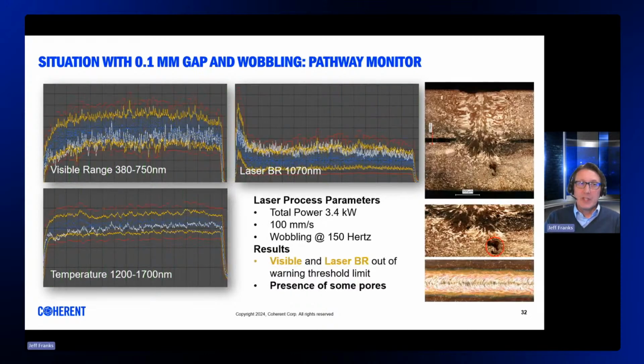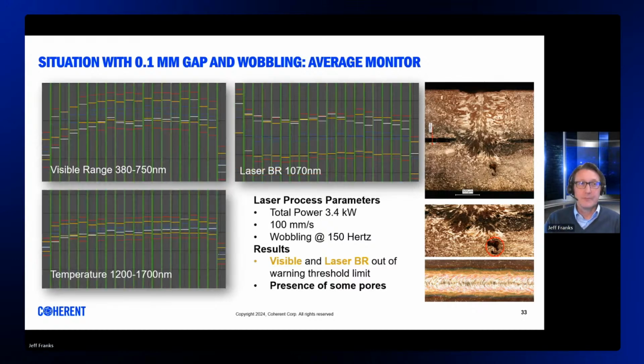Now we can see the effect when we reintroduce the gap condition to the wobbling process, in this case 0.1 millimeters. We observed the wider warning conditions for the process and back reflection data were breached, and that in the actual weld, some pores started to be generated, although the top surface appears well. We see again that the weld process data is more stable and clearer when the average monitor filter is applied.